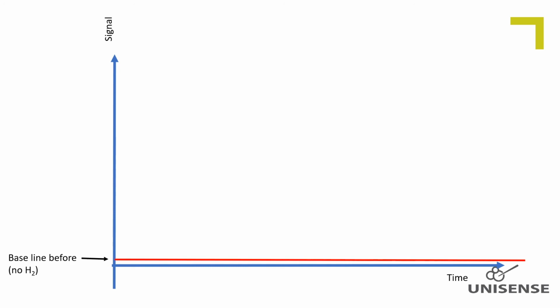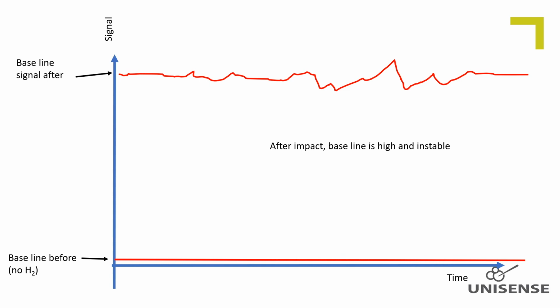A physical impact like a drop could also damage the glass insulation of the platinum wire connecting the working electrode. This will typically result in an elevated and noisy baseline signal due to exposure of polarized platinum to the electrolyte. Chemical reactions taking place on the exposed platinum surface will create a current which will overlay the working electrode generated current. The size of the baseline increase will depend on the degree of damage to the platinum wire insulation. Such damage cannot be repaired.